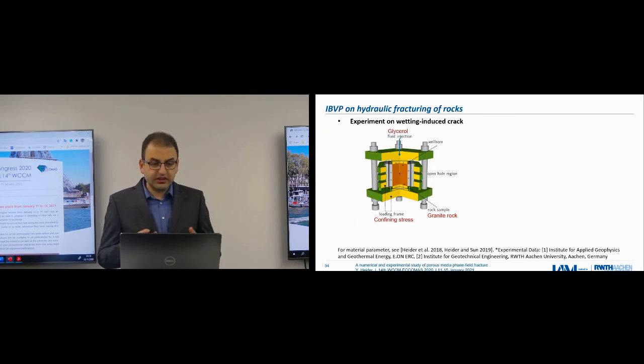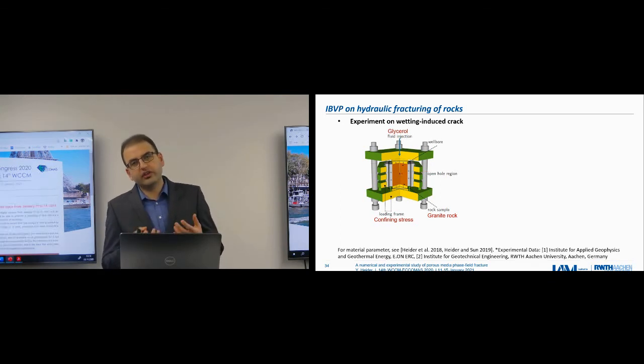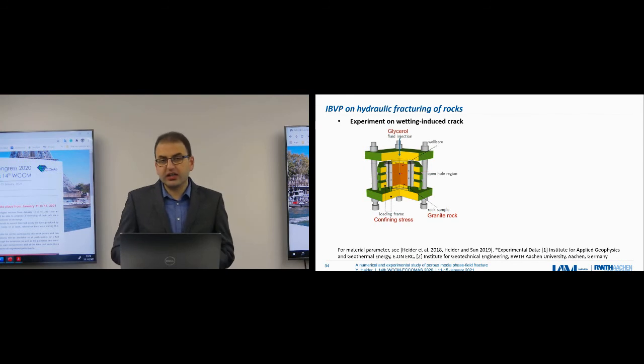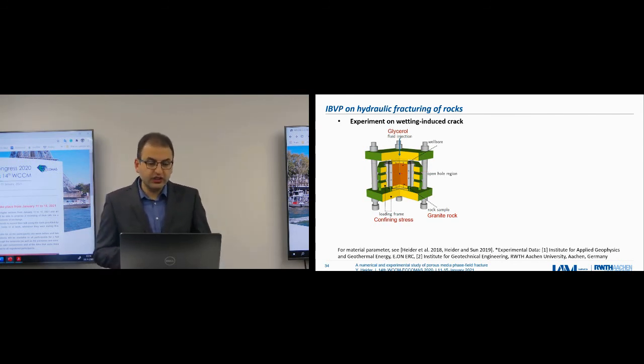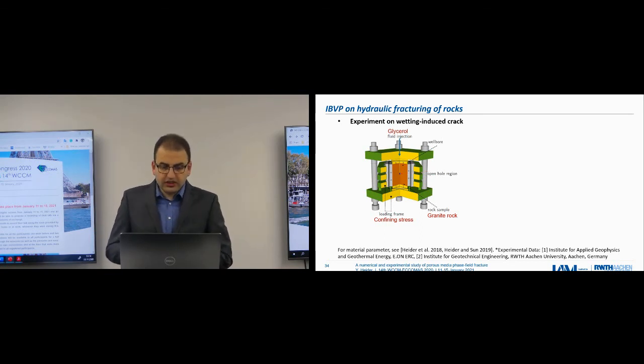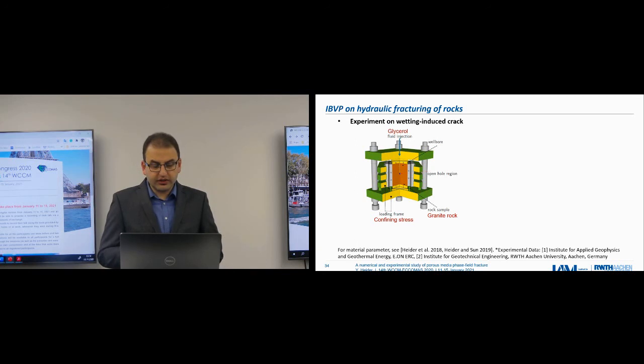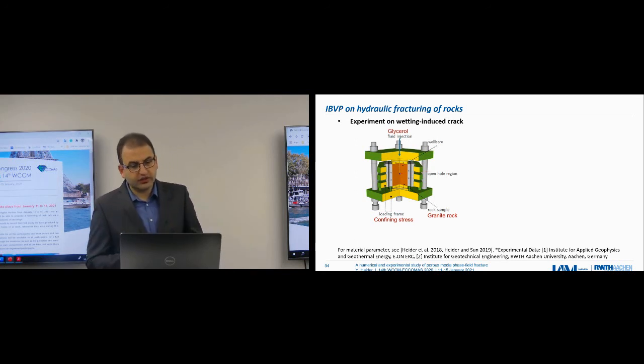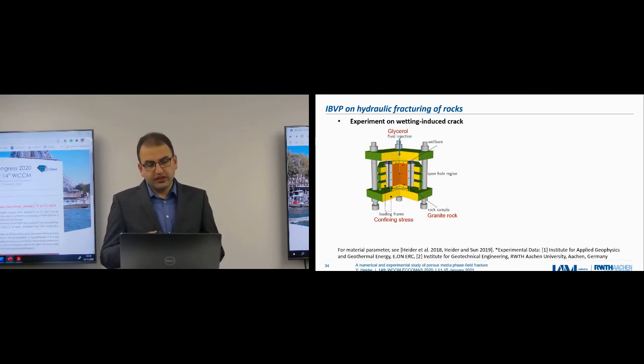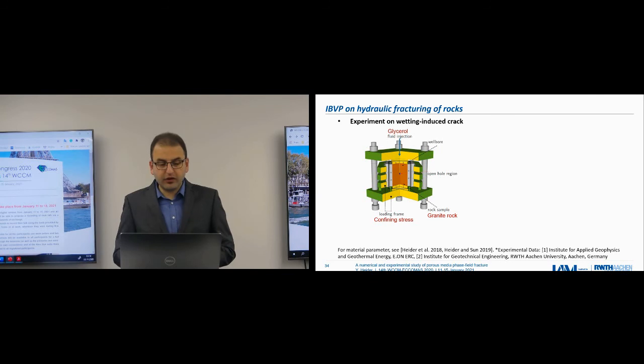The second example is related to hydraulic fracturing. This is the opposite process. Here we inject fluid in the domain, and we had a number of experiments in our institution. We had this triaxial testing machine, in which we have a sample of rock in the middle of this machine, and it's subject to confining stresses. This sample has a wellbore, and in the middle of this sample we are injecting fluid. Our choice is glycerol. It's a highly viscous fluid, and the reason for this choice was that this highly viscous fluid leads to a kind of stable crack propagation process. This fluid was also mixed with some colors in order to determine the radius of our crack.